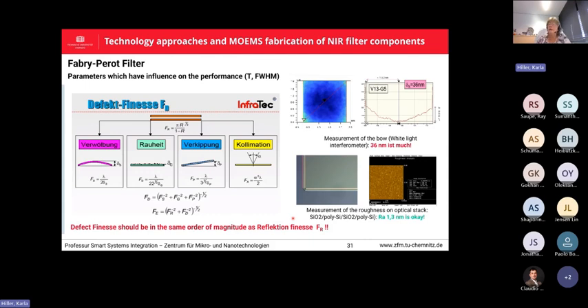So this looks all easy, but the problems come with the influence on the parallel adjustment of the two plates. Any bow would lead to so-called defects. Any roughness would lead to defects, even if the elements are not at the same angle. This would lead to some defects. And also if the light comes not directly perpendicular, but at a certain angle, this also gives some defects. So we have analyzed this for the different influences, and we found that the roughness is not so much of a problem. So our deposited layer with a roughness in the range of 1.3 nanometers is fine.